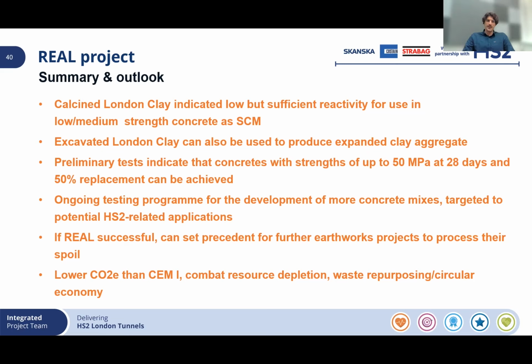We can also use it to produce expanded clay aggregate, although we already knew that to an extent. Preliminary tests with the LC3 type of binder reveal that we can go up to 50 megapascals. But now with the new binders we are considering, with 50% or even 70% calcined clay replacement, we may be able to achieve these high strengths with a binary binder formulation like Portland cement and calcined clay only. We have an ongoing testing program, as I mentioned, to finalize the concrete mixes.